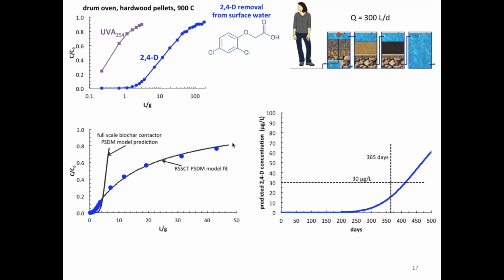And with this system, we recommend people to change their char once per year. So what this is suggesting is that at a year of operation, this system would be expected to be removing 2,4-D at about 80 or 85% after 1 year. And that for a high concentration of 2,4-D coming in of 100 micrograms per liter, that would be below this level of 30 micrograms per liter, which is the World Health Organization guideline value. So the World Health Organization says, if you believe them, that it's okay to drink water that contains 30 micrograms per liter or less 2,4-D herbicide. So we chose that as a sort of indicator of whether our system is performing and providing water that maybe people would consider acceptable for consumption.